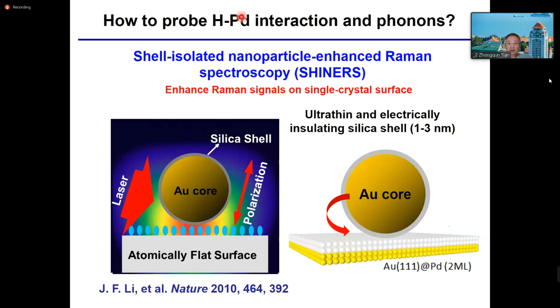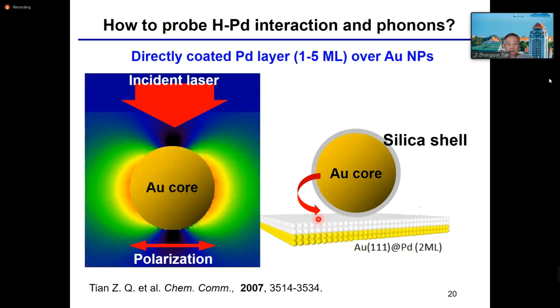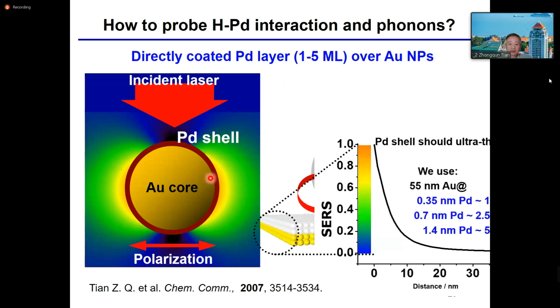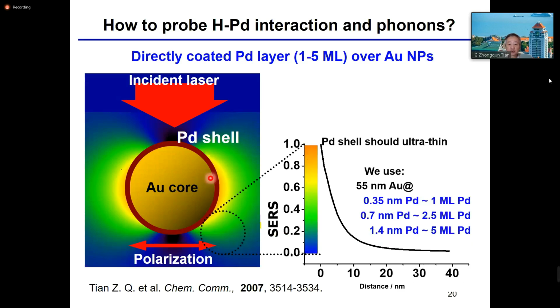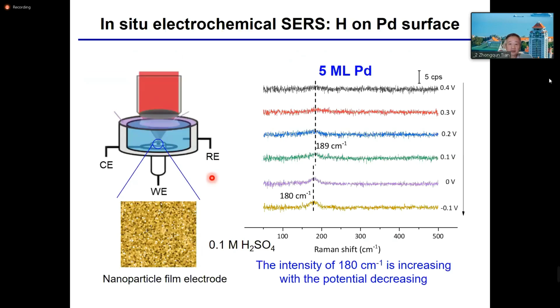So we want to detect and see if it's possible to get the signal from this type of hydrogen palladium, or even phonons for this thin layer, because we cannot get any phonon signal of Raman spectroscopy from bulk palladium. Unfortunately, we have failed so far to get the signal of hydrogen, palladium, or the phonon of the film. So we changed the idea. We overcoat an ultrathin palladium shell on the gold nanoparticle, because the signal is much stronger.